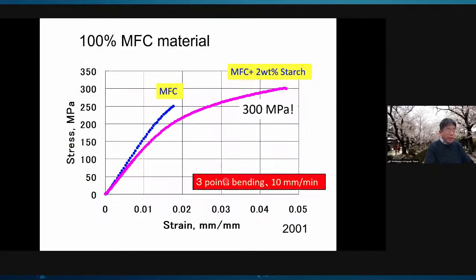This is a stress-strain curve of 100% MFC. The strength reached 250 megapascal in bending because of the hydrogen bonding between the CNF network. And when we add oxidized starch at just 2 wt%, the strength reaches 300 megapascal. I was so excited with these results.